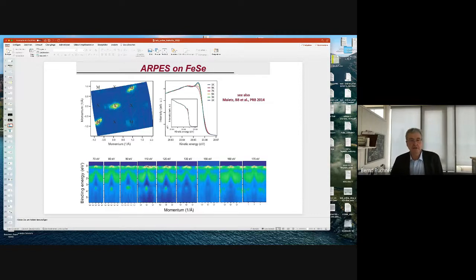And what you see here are data measured for different photon energies. This helps us a little bit to deal with the matrix elements. This is a detail which I do not discuss in detail. So the first thing is, yes, we have states here at the Fermi energy as predicted by band structure, but we also have something here at higher binding energy.